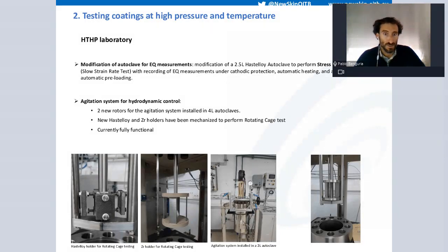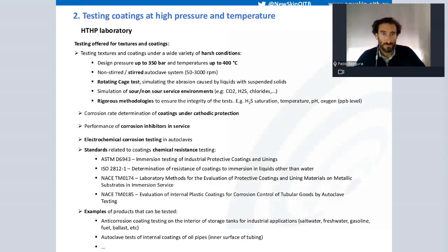Here you have some pictures of the holders and the samples that are rotating. This has to be a video, but it cannot be played right now. It can be seen how the samples are rotating and then are introduced in the autoclave. And then when it's closed, we can test the conditions that we have defined. Here are some specifications that we can test. We can test up to 350 bars and temperatures up to 400 degrees, rotating or not rotating samples.